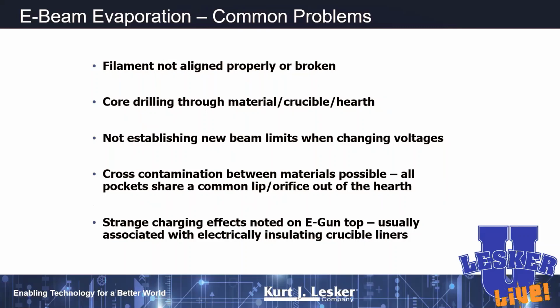What else? Things that go wrong. Typically, it's related to the filament not being aligned properly. I'll show you an image in a second. Core drilling: if you don't move your beam around, you're likely to core drill through your crucible into your materials. Bad, bad, bad. If you don't keep your multi-pocket gun clean, you're going to have cross-contamination issues there. And then I mentioned this charging effect. You've got to use electrically conductive crucibles with electrically conductive materials.